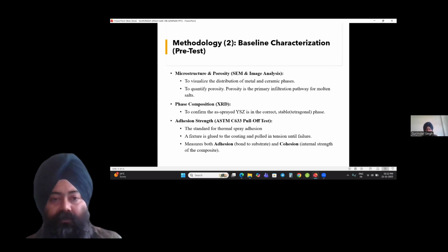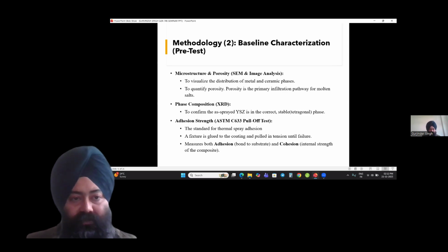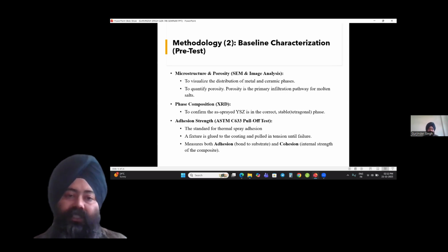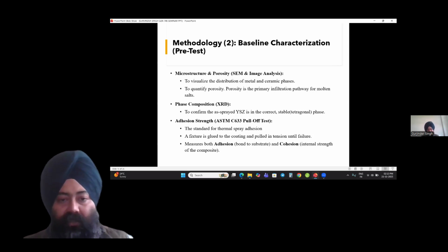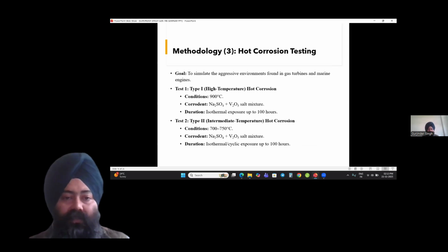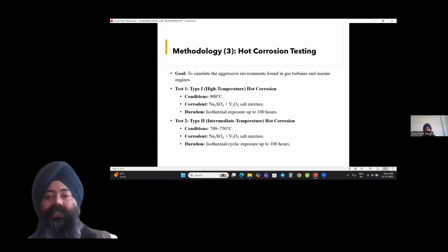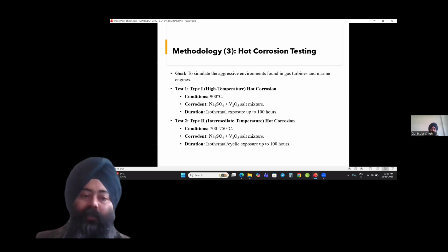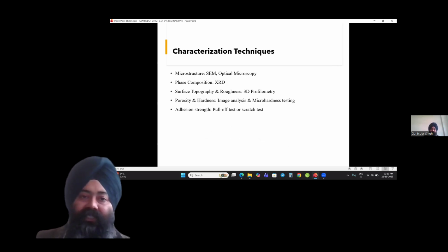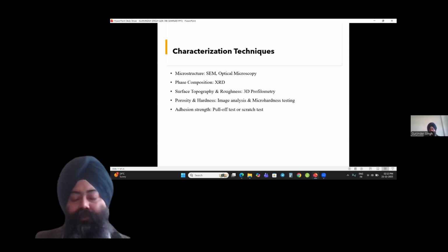The second methodology is microstructure and porosity testing. For microstructure, we are using SEM analysis, XRD for phase composition, and for adhesion strength, we are planning to use an adhesion pull test. Then hot corrosion testing, in which we will test our material in both temperature conditions, type 1 and type 2. Characterization techniques: for microstructure, SEM and optical microscopy; for phase composition, XRD; for surface topography and roughness, 3D profilometry; for porosity and hardness, image analysis and micro hardness testing; for adhesion strength, pull-off test.